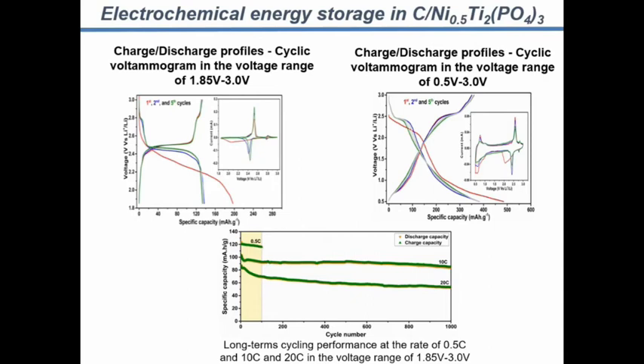The CV curves confirm that we have a good reversibility because the anodic and cathodic peaks overlap during the first 5 cycles. But what we got as a very fantastic result is when cycling our material during 1000 cycles. It's a very huge number of cycles. And under 10C or 20C regime, this means we use very high currents of discharge or charge. We have a good reversibility of the process during 1000 cycles. The capacity is still maintained at a stable number of 100 milliampere hour per gram at 10C, for example. This is very interesting. That also confirms that the phosphate exhibits good structural and thermal stability during